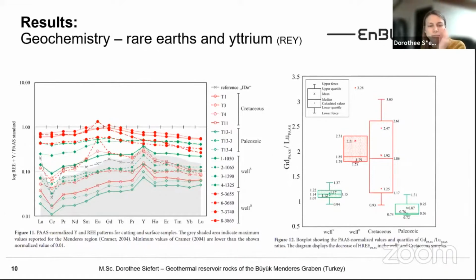But if we compare, in addition, what is shown on the right figure, the samples of the deep well section and Cretaceous samples exhibit higher gadolinium to lutetium ratios. So this means that the Paleozoics and the shallow well samples have a lower ratio here, which indicates no significant decrease of the heavy rare earth elements.